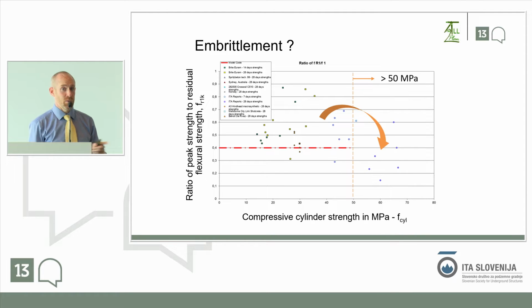I look at it slightly the other way, which is, why do we need that strength? If we have stresses in our tunnel lining of 2-3 MPa, and we have a compressive strength, obviously we're talking about an average value there and ignoring bending, but we have a strength of 60 MPa, maybe we're over-designing. And so going back to Wolfgang's point, if a little bit more intelligent design could help us to optimize that.